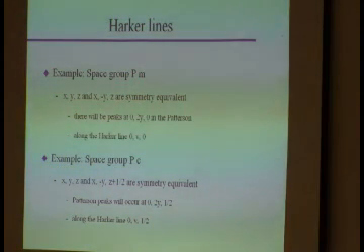Now notice, mirror. How many dimensions does that symmetry element have? It's a mirror what? It's a two-dimensional element, right? It's a mirror plane. Glide, what is it? What do we call it? A glide plane, right? So once again, it's a two-dimensional element. The translation may only be in one direction, but it's a two-dimensional symmetry element. Both of them make Harker lines because they change one coordinate. Okay?